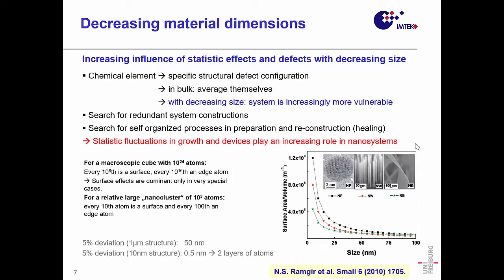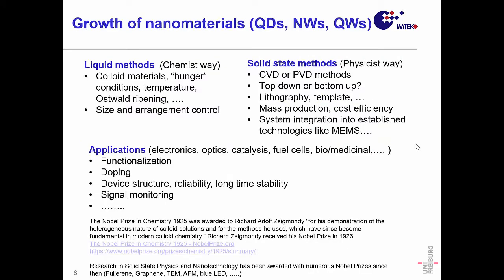And that could actually already change the quantum luminescence of your materials. Okay, so how can we grow nanostructures? There are different methods to grow nanostructures, quantum dots, quantum wells, nanowires. The chemist prefers the liquid methods, that means the colloid methods, and then what you're doing is you grow that in a colloid, in a suspension, in a solution under hunger condition, controlled temperature, Ostwald ripening, and so on. I just would like to state that there was already a Nobel Prize.